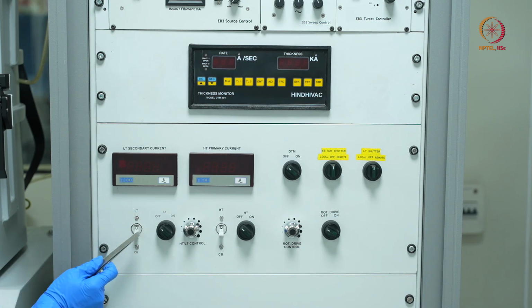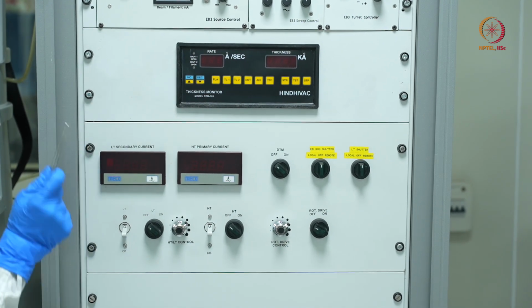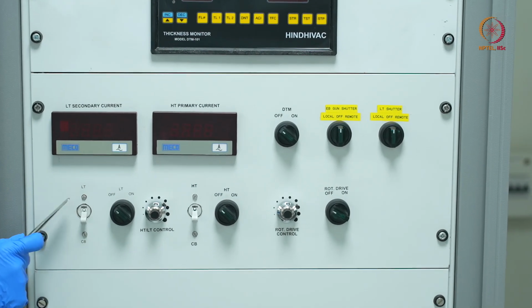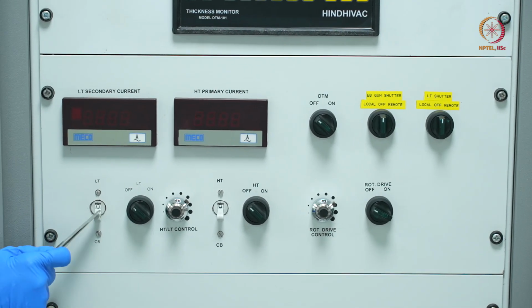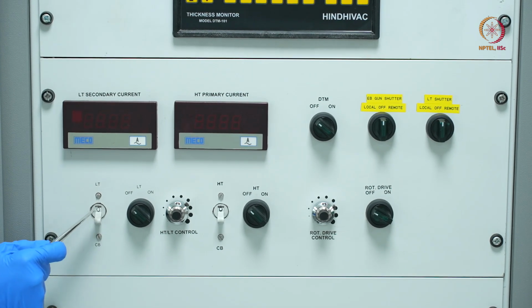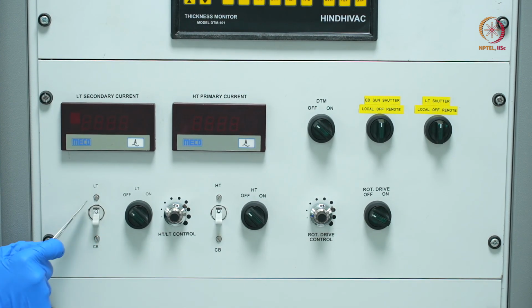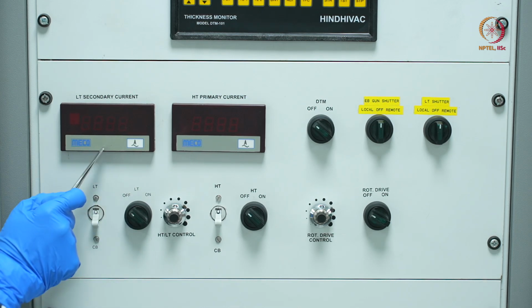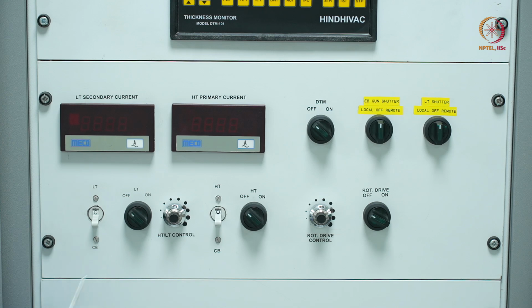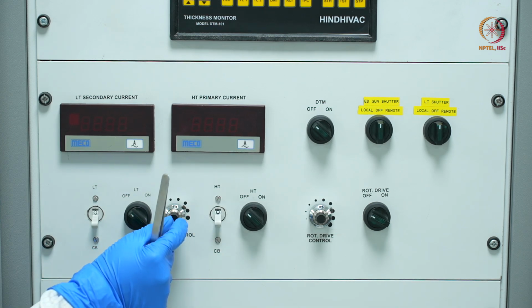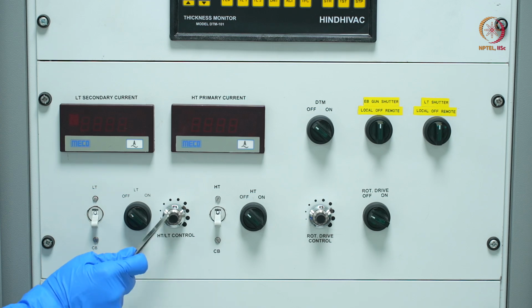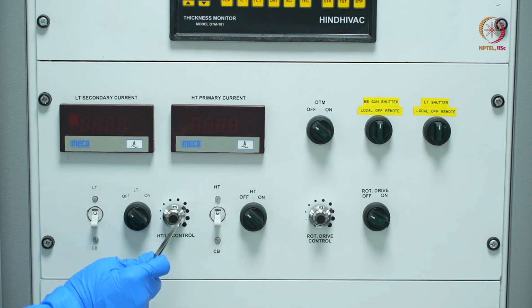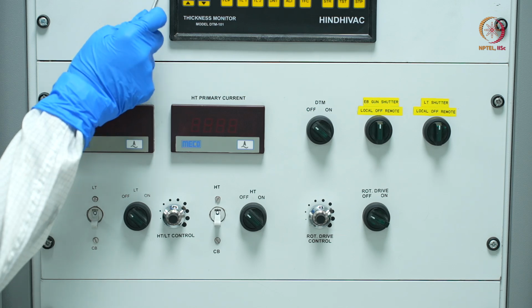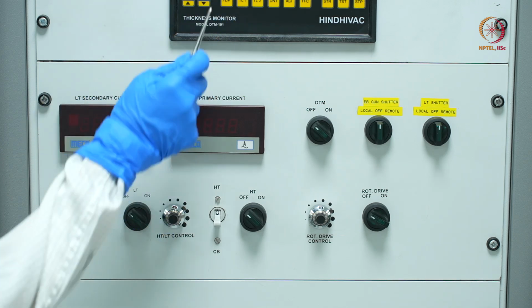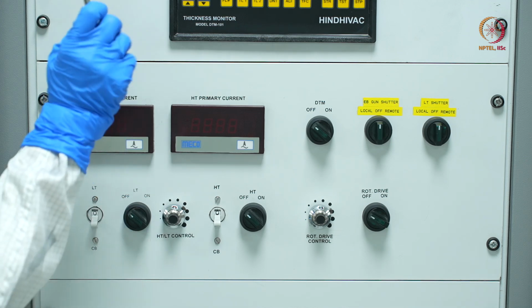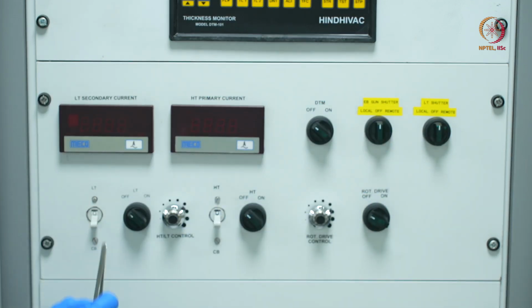This is a circuit breaker. This tool has two options, either to go for e-beam or thermal. So this will switch the supply voltage to the thermal basket, and this is the knob to switch on the display for the LT current, and this is a knob wherein I'll increase my current for preheating, as well as to a point where I'll see some deposition or the deposition rate is increasing, and I'll stop at that current and open the shutter to start my deposition.